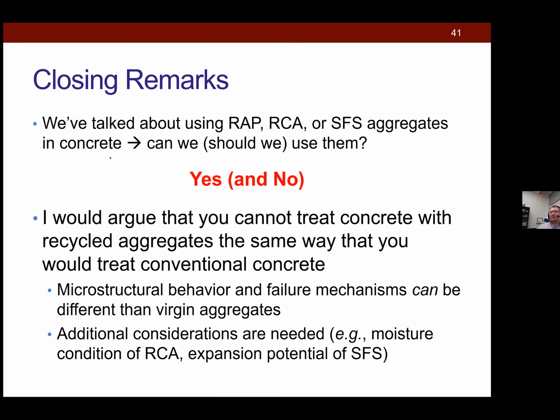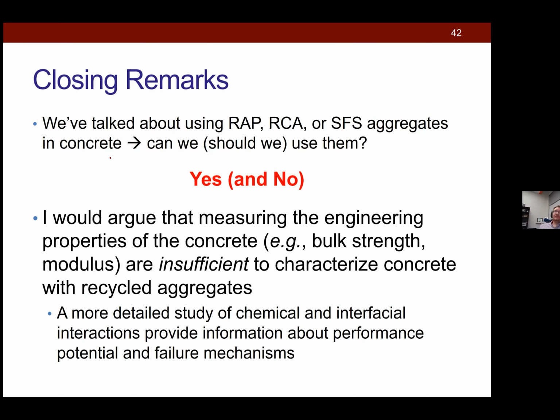So if these failure mechanisms are different, do we need to start changing our design procedures? Okay. And lastly, the mechanical performance here, again, since the failure mode is different, measuring strength and modulus is not giving you the whole picture. Okay. If we had more time, I'd talk a little bit about the slab capacity study we did, because we showed that even though concrete with RAP had a lower strength and a lower modulus, its slab capacity was actually increased relative to the control.